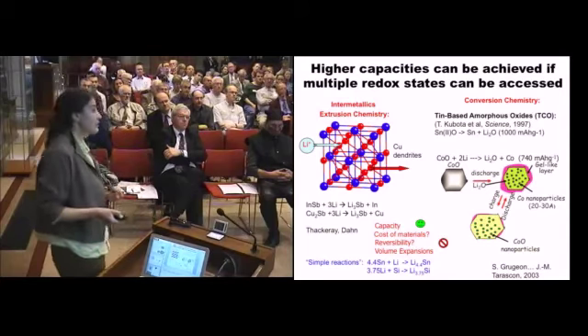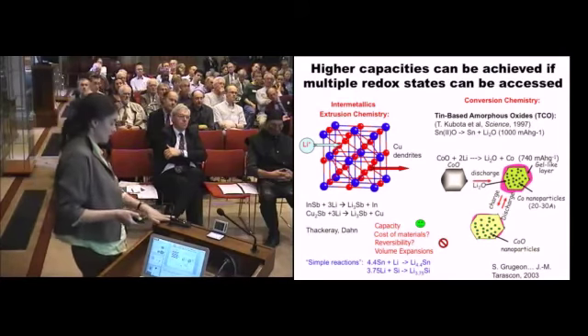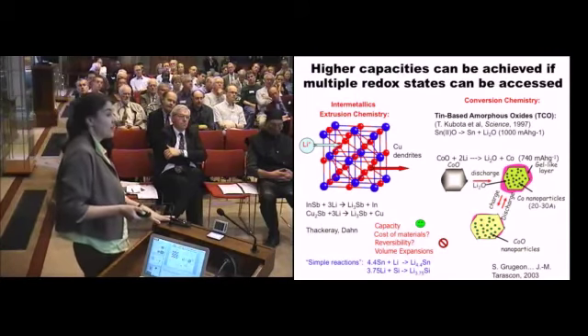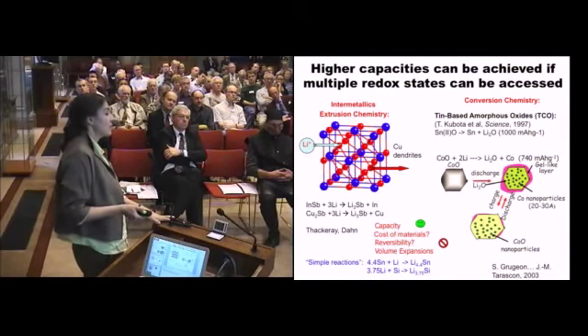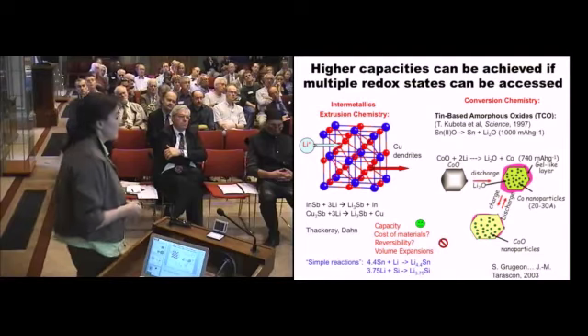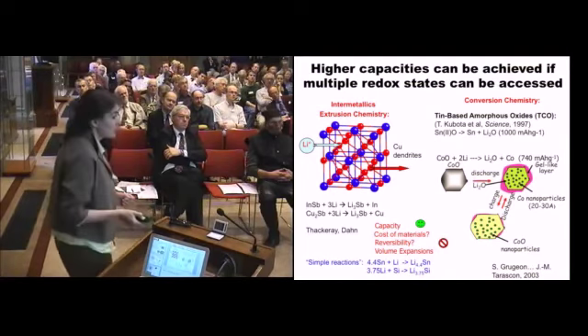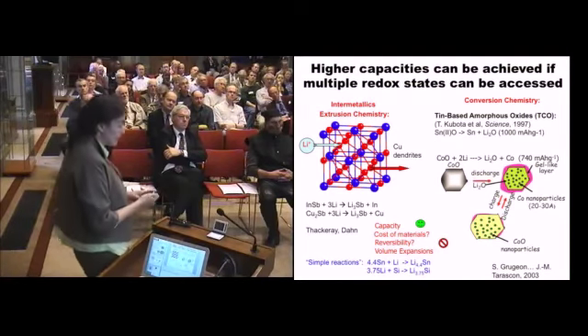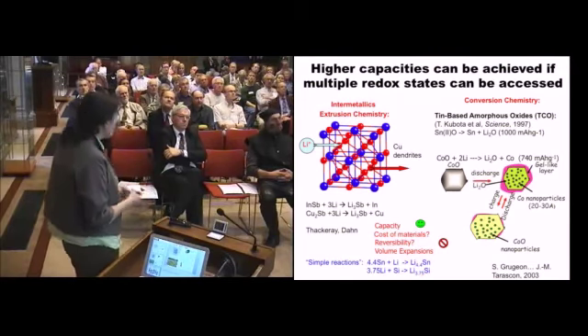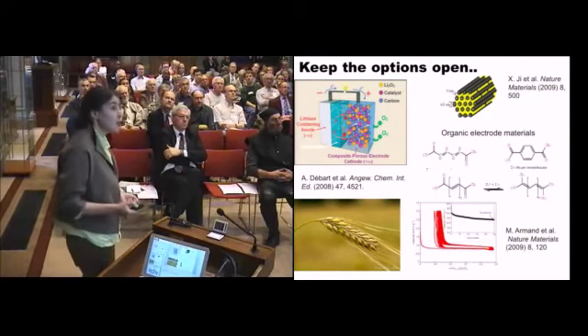And then you've got simple reactions, and this is what I want to come back to later in my talk, such as lithium reacting with silicon. Here you can take a silicon matrix and react it with almost 4 lithiums to make a lithium silicide. But the problem with this chemistry is you've got very large volume expansions. So there are a lot of different options, and there are other ones that I haven't talked about.